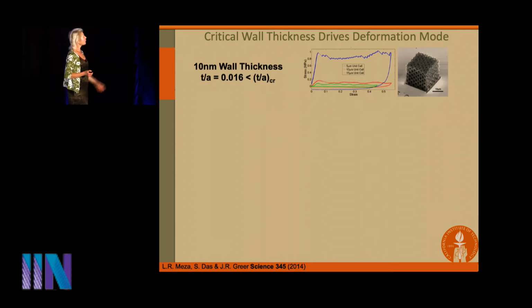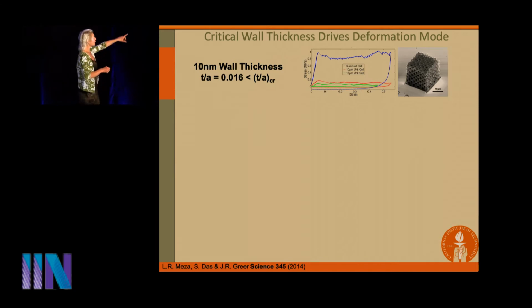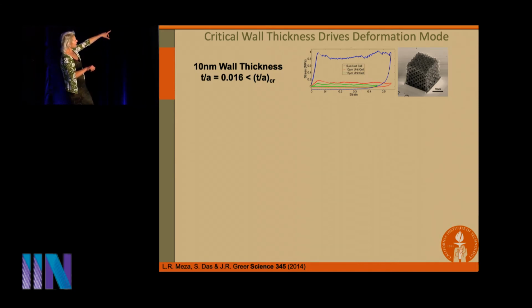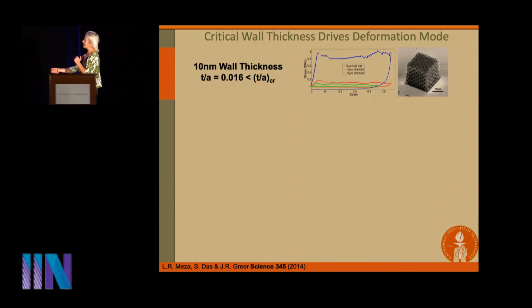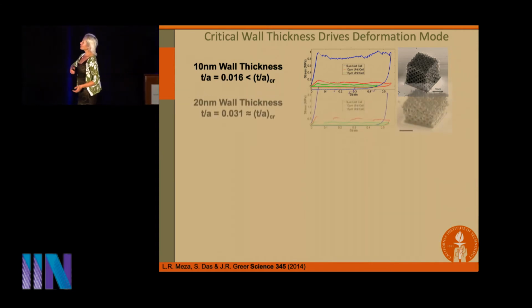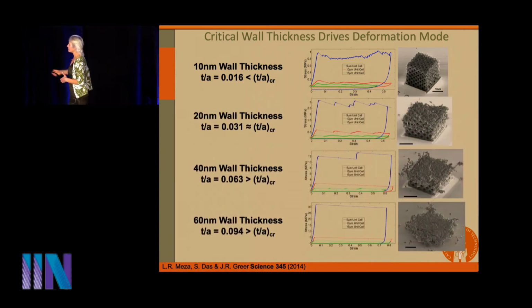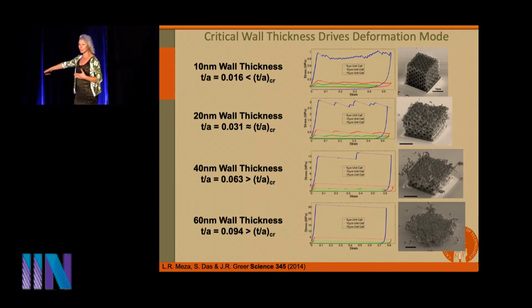So for the 10 nanometer wall thickness, that's the sample that you saw recover. You can see that no matter what the unit cell size is, every time it recovers. This is an image of one of these samples after the deformation, which you would never be able to tell the difference because it looks the same. And of course, this seems to be checking out. Now, as we increase the wall thickness, you can see the deformation is becoming much more jerky, much more drastic, much more discrete. And then this last one doesn't even try to recover at all.